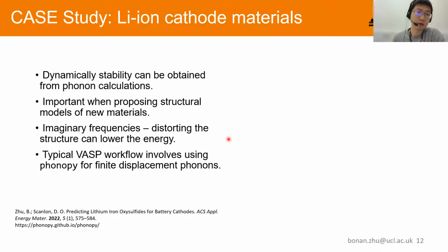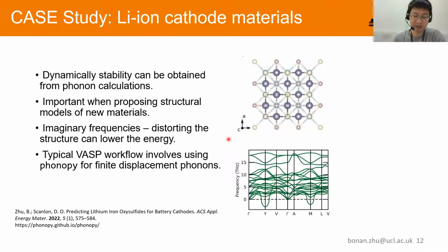The other very important thing is dynamical stability, because you can essentially build any crystal structure you have and put it into a calculator that would give you energy and force, but whether this is really stable or not is not that obvious. So what you do is a phonon calculation through finite displacement. You move the structure a little bit, displace the atoms, and then the forces will be post-processed to allow extraction of these phonon dispersions.